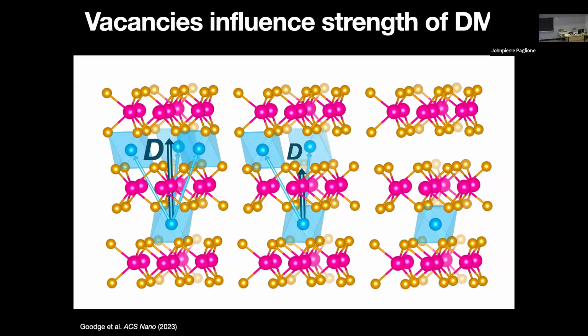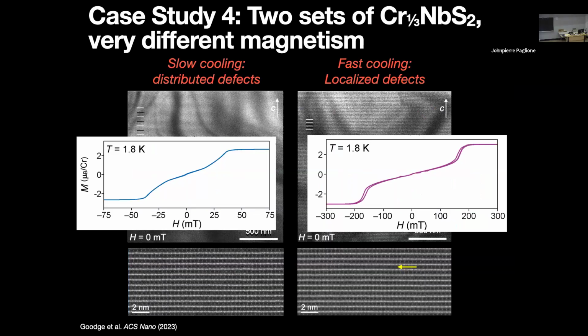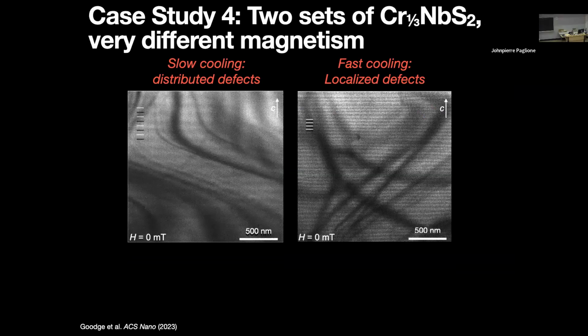And if I showed you the Lorentz TEM, we can show, as we apply the field, how these textures that I'm showing here wind and unwind. And you can actually see them pinning and unpinning at defect sites. It's actually pretty cool. Whereas this one is very smooth, it's continuous. Whereas in these, you see this pinning and unpinning, and I can show you that later if you're interested. And so that's the picture that we had. That then motivated us to try to understand a little bit more about the disorder question. And then your second one was basically about whether that model is just considering the nearest neighbor interactions. It's a Monte Carlo model using some parameters obtained from DFT, which is just considering the nearest neighbor interactions. It's a relatively simple model, but it works really nicely to predict what we actually end up seeing in an experiment. I don't know if that answers your question.